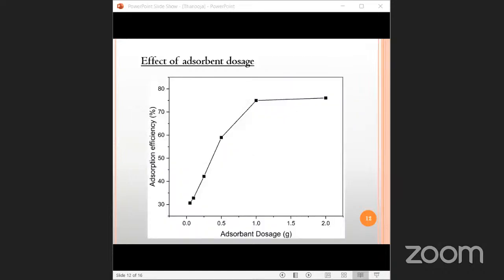The effect of adsorbent dosage. The effect of adsorbent dosage on percentage removal of chromium ions was studied by varying the dosage from 0.05 to 2 gram. As we can see in the graph, there is a sharp increase in the adsorption efficiency initially, then the rate slowed down. On further increment of the dosage, there is no further increase in the percentage removal. Only a slight increase is visible.